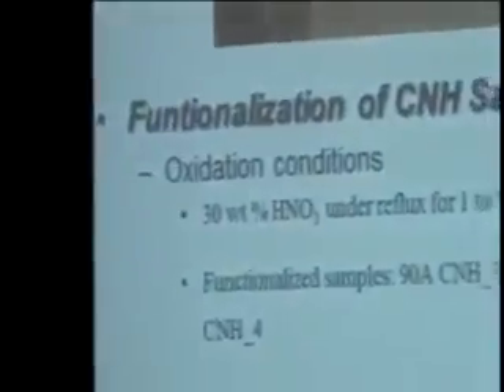So all the results on the yield in the previous slide were based on 1 Erlenmeyer flask. So in order to further improve our production, we had to use 6 Erlenmeyer flasks and then run the experiment for 30 minutes per flask. After the carbon nanotubes had been synthesized, we functionalized our samples by employing the liquid oxidation method, and then